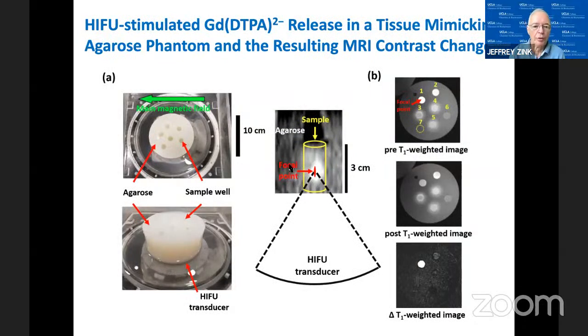So here we show our phantom with a variety of sample wells. We put our sample, in this case our nanoparticle with gadolinium in it. We stimulate it with the HIFU, and the middle one shows the focused high-intensity ultrasound focused in the middle of our sample system. And what you see there is an MRI image. You can see that where the focal point of the ultrasound is located is where we see the huge change in contrast, and we can measure it.